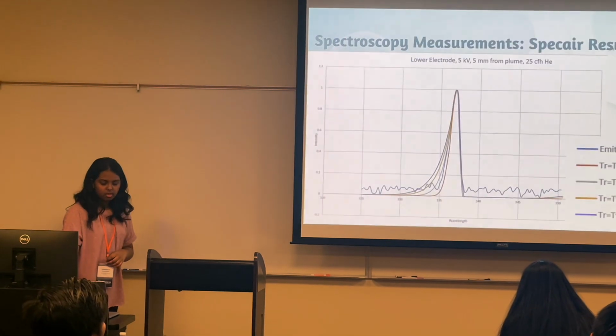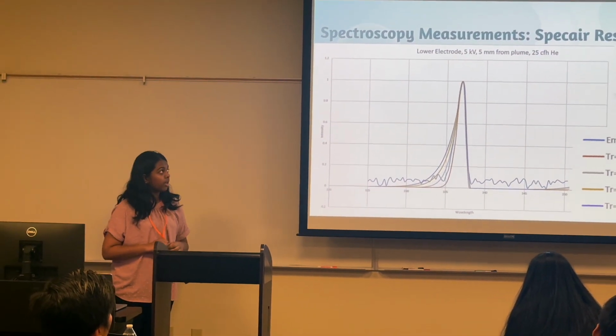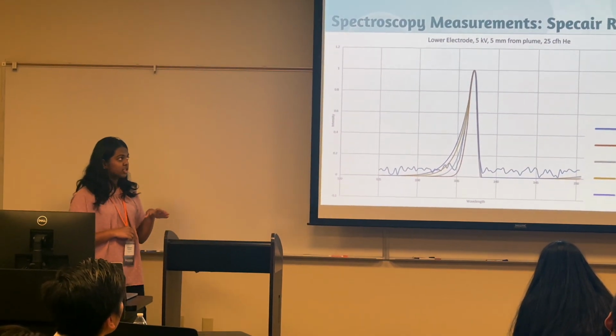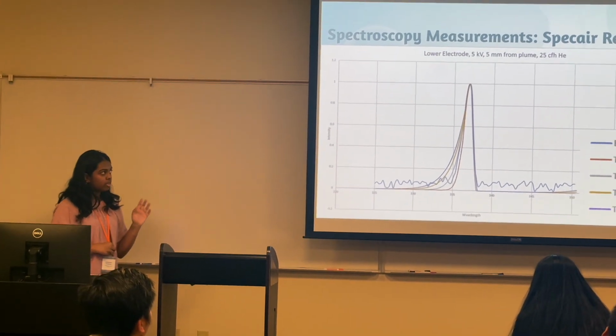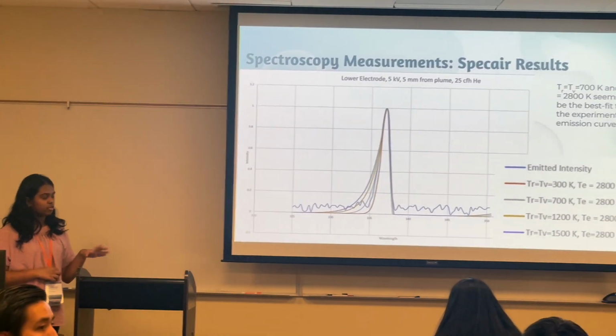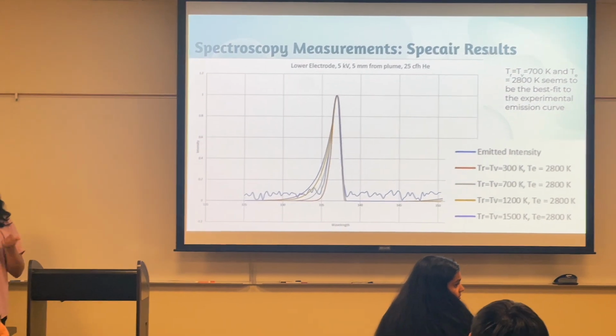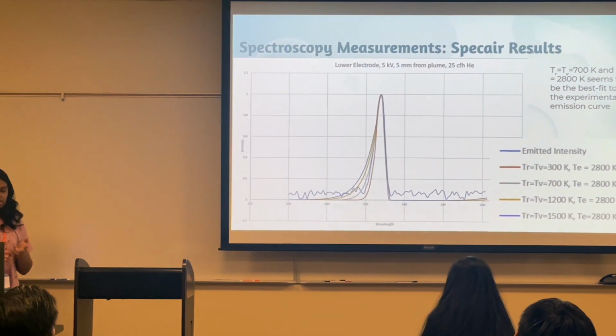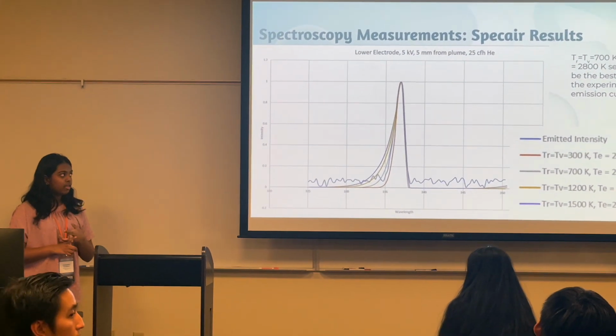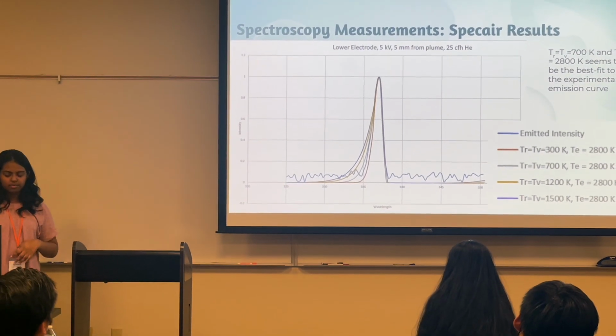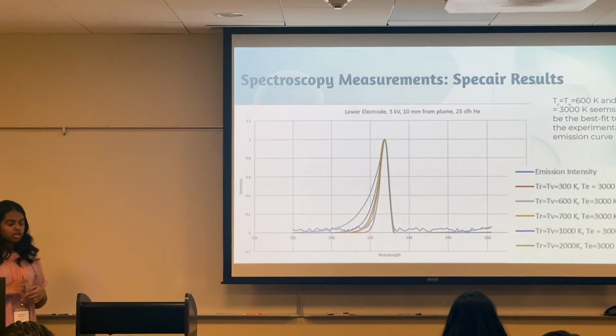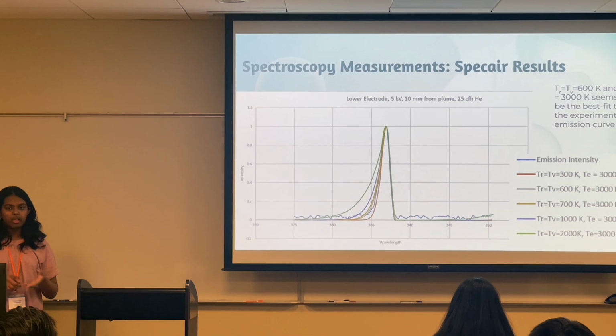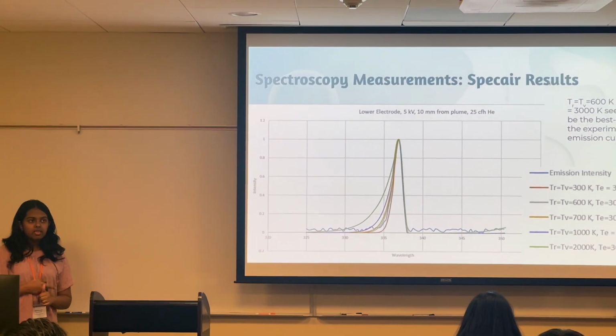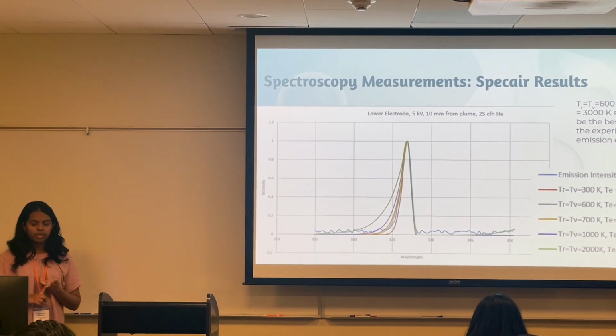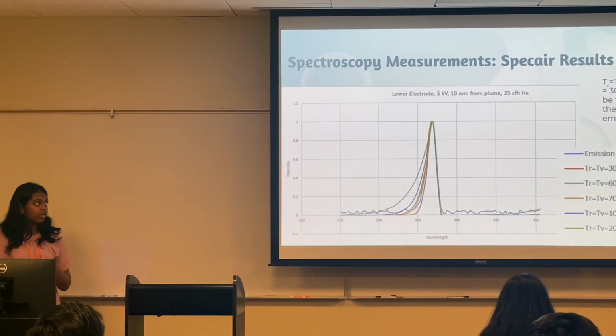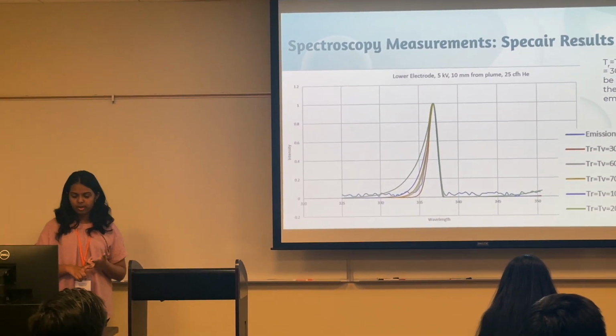Okay. So over here, for the lower electrode at 5 millimeters from the plasma jet exit, we found that 700 Kelvin and 2800 Kelvin, 700 being for the rotational and vibrational temperatures, and 2800 being for the excitational temperature, was the best fit for our curve. For the lower electrode at 10 millimeters from the plasma jet exit, we found that 600 Kelvin for the rotational and vibrational temperatures, and 3000 for the excitational temperatures was the best fit for our curve.